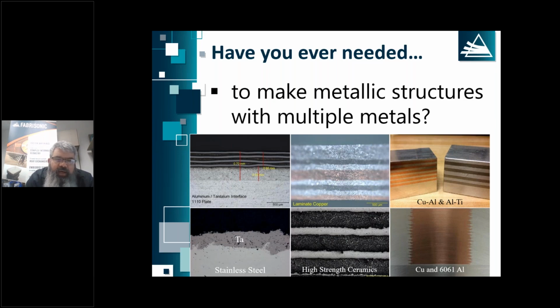Now, if you were going to take the bottom right there, aluminum and copper, and you melt that using a traditional melt-based approach, when that resolidifies, you're going to get an intermetallic. And the problem with intermetallics is they tend to be very brittle, almost like a glass. So they're not a material that is typically desired in engineering. Because we're not getting hot, because we're not creating any sort of melt pool, we can mix these dissimilar metals layer by layer without having to worry about the metallurgical consequences of mixing two dissimilar metals.